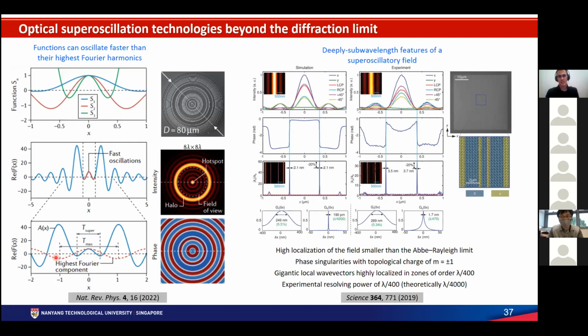How do you generate these super-oscillatory features? Well, you can use a nanostructured phase or intensity mask, in this case a silicon phase mask that you see here. And typically you will see a hot spot appearing in the far field. The hot spot is sub-wavelength, it breaks the Abbe-Rayleigh limit, and has been used to show imaging that goes almost to lambda over 8, lambda over 10, also real live in vivo imaging of real cells, neurons in that case.